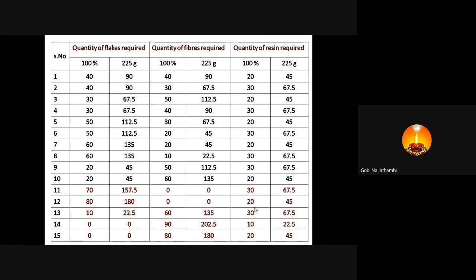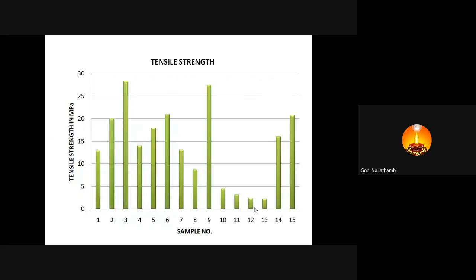But at the same time, if you see samples 14 and 15, the tensile property is somewhat higher, not like 11 and 12. So 14 and 15 are giving higher values because the fibers and resin can be integrated during the composite manufacturing, and then it will give a higher tensile strength. So when the proportion is optimum, the tensile strength is highest in 3 and 9. If you see the flakes, resin and fiber proportion in samples 3 and 9, these two samples are giving higher tensile strength.